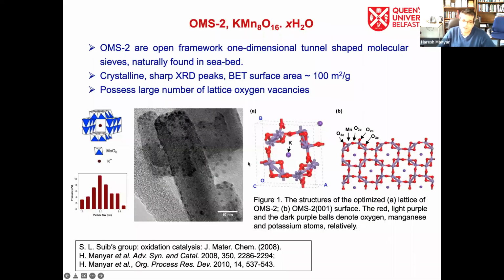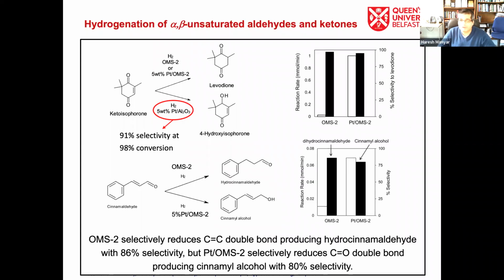These are nice crystalline porous unidimensional materials, which have multiple oxidation states of manganese, and the structure is hungry for oxygen, because it has a huge number of lattice oxygen vacancies. Because of that, it's a very active catalyst for a number of organic transformations. For example, let us look at the selective hydrogenation of aldehydes and ketones. We can easily convert the ketoisophorone to hydroxy isophorone or to levodione by tuning the catalytic materials. Very high selectivities in the order of 91% at a high conversion of 98% can be achieved here.